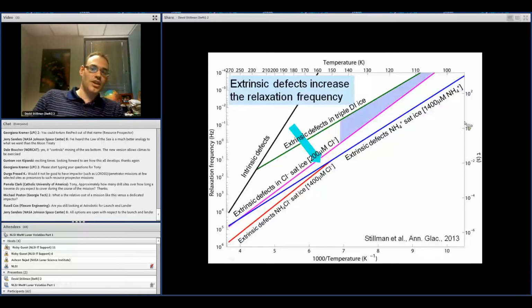The reason why this is important is because on the moon, this is where you might expect to find subsurface ice, at temperatures below 145 K. So in this blue shaded area is where we should find our relaxation frequency of ice. Now, there are a few things that might push it over. If we get radiation defects and they act as extrinsic defects, we might actually get higher frequency relaxations. This would be a good thing because using dielectric spectroscopy, we can really only measure this relaxation frequency to 10 to the minus 4 hertz.